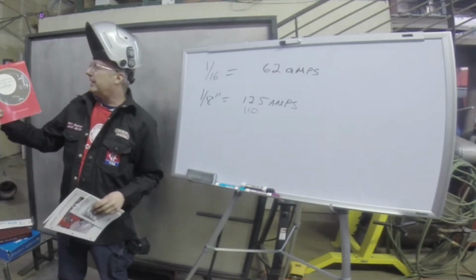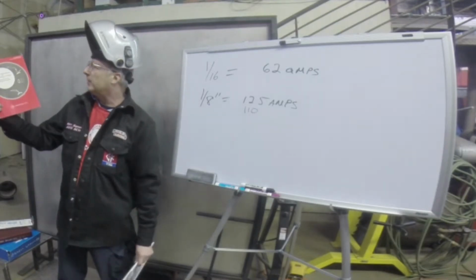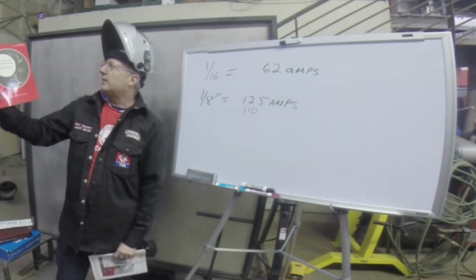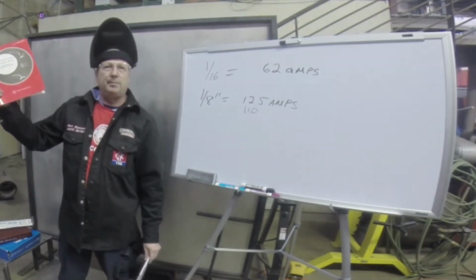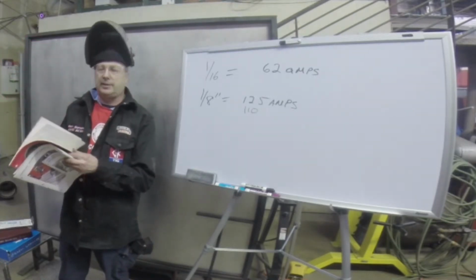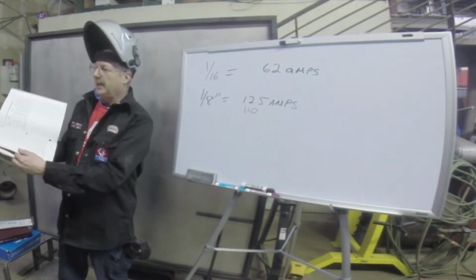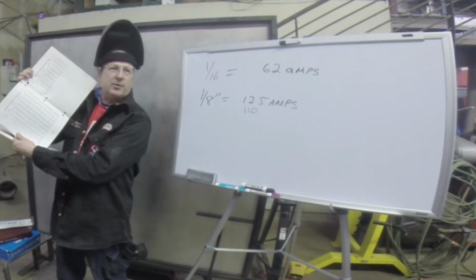Also, the American Weld Society sells different kinds of specifications. This one here just happens to be recommended practice for gas shielded arc welding of aluminum and aluminum alloy pipe. And then here are charts that'll tell you based on your pipe diameters and thicknesses what your amps and your travel speed should be.